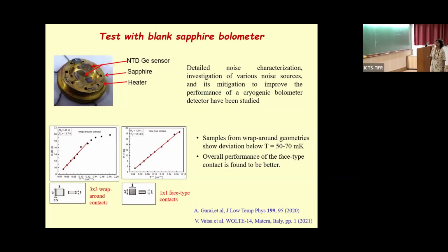The next step is that you also have to improve the contact making on the sensors, and we found what gives us better linearity even down to about 50 millikelvin temperature. Ultimately, we still have to go down to 20 millikelvin, but these sensors are now found to work well to 20 millikelvin. Now, we have to learn overall the noise.